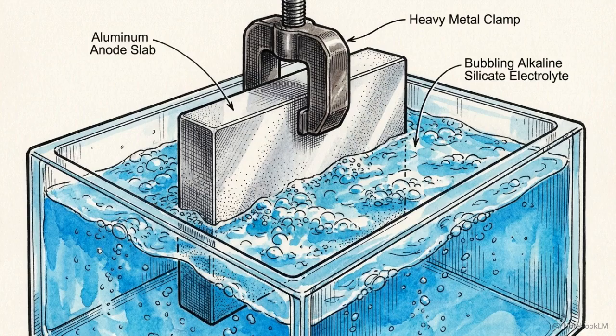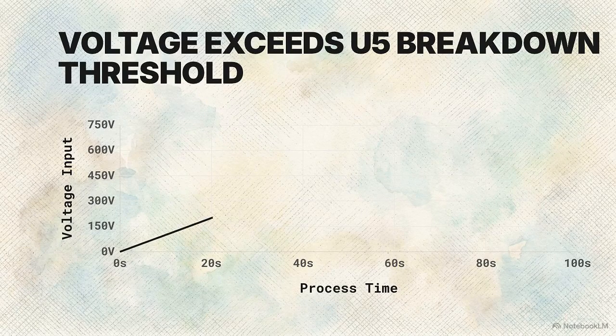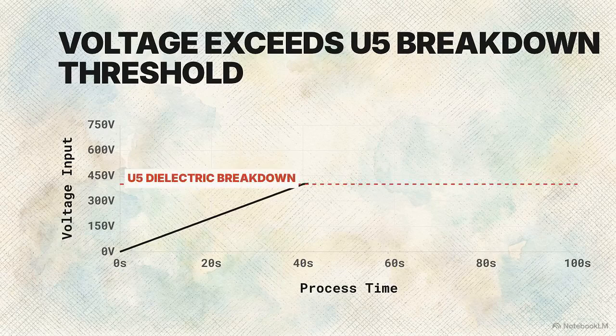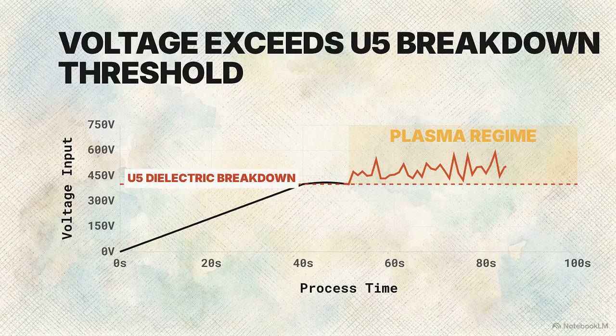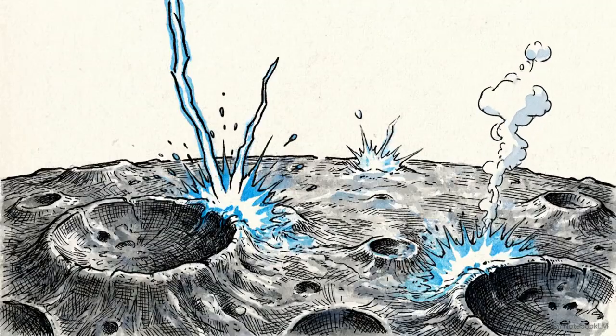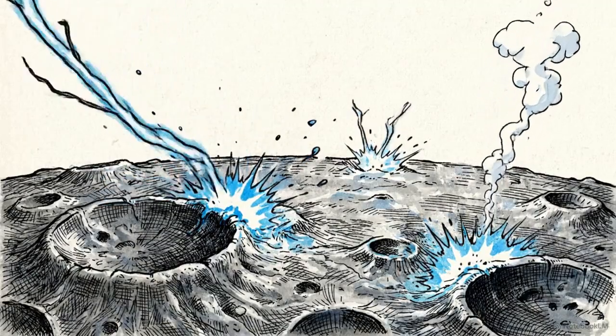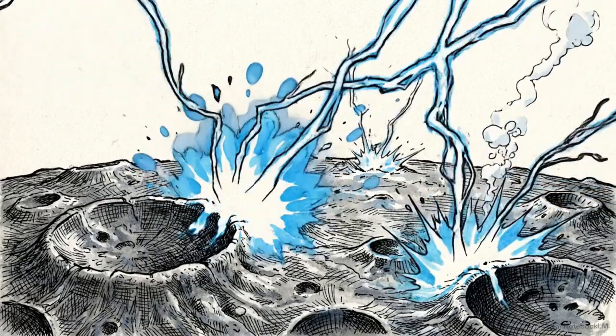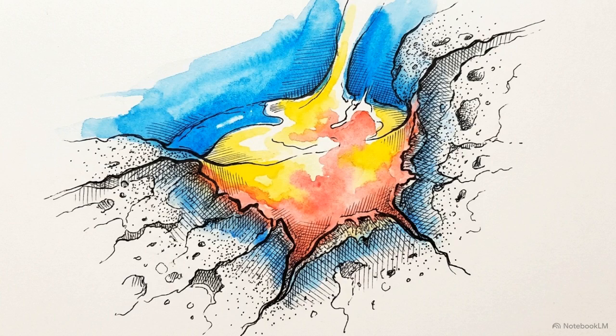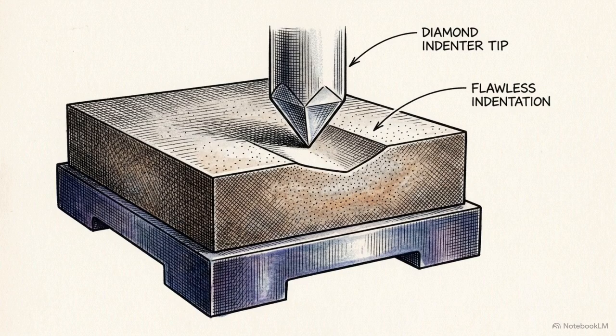Building the new architecture starts by immersing the bare AA2024 substrate in an alkaline silicate electrolyte. As the voltage increases during oxidation, it reaches the U5 threshold, the point where the dielectric properties of the oxide layer break down. Micro-arc oxidation intentionally pushes past this limit to weaponize this breakdown. Entering this plasma regime generates microscopic electrical discharges across the metal surface, reaching temperatures between 3,000 and 10,000 Kelvin. These thermal discharges locally melt the aluminum, forcing it to react with the electrolyte before it rapidly solidifies. This process grows a thick ceramic layer composed of alpha and gamma alumina, reaching a hardness of nearly 1,800 Vickers.